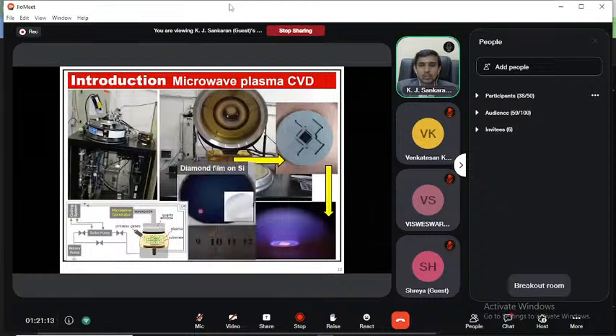Now after the growth of the diamond film on the silicon substrate, how does the diamond film look? It is a dark bluish color. This is the flat silicon substrate without any diamond growth. These are the diamond films grown on the silicon substrate. It's a very thick diamond, more than a micron thick, so it shows a dark bluish color. Depending on the thickness, interference patterns occur, and the color also changes with the diamond film.